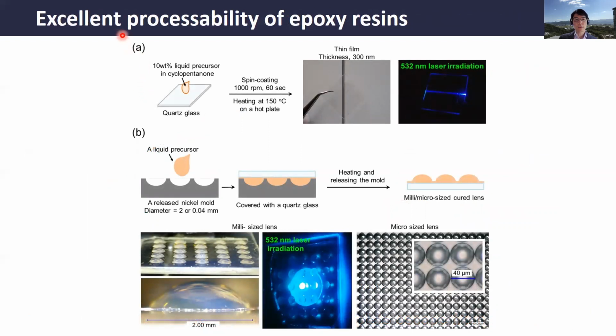And another very important feature of this epoxy resin is the excellent processability. By just spin coating, you can get a nanofilm with a thickness of 300 nanometers. And this again shows nice upconversion in air thanks to the good oxygen blocking ability of the epoxy resin. And you can mold it into more complex shapes. Here is a microlens shape, and you can get upconversion in this microlens.